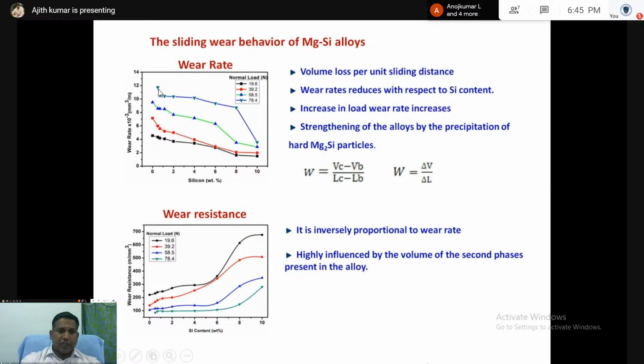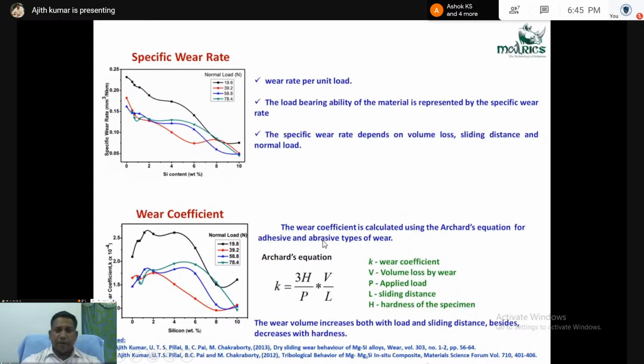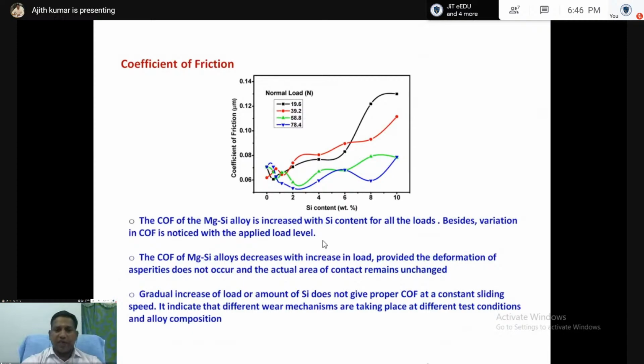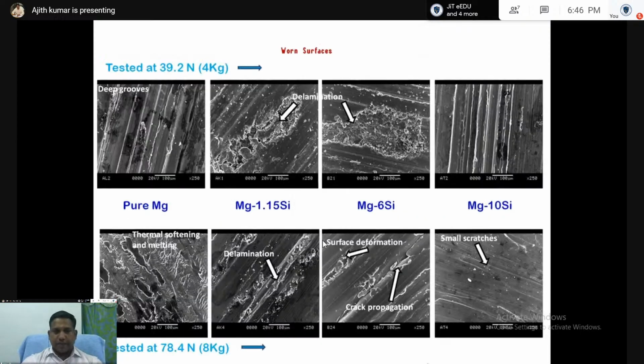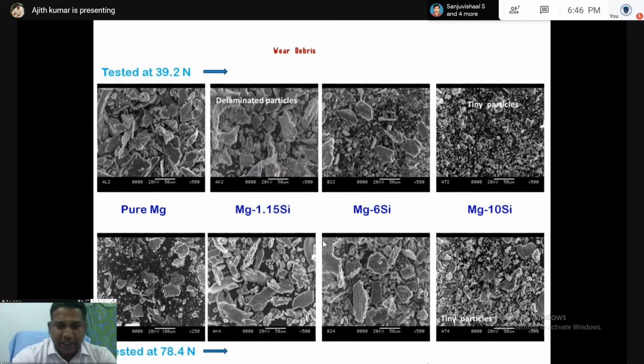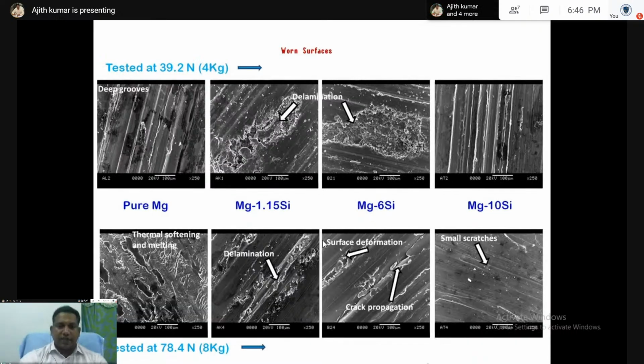So with respect to the silicon addition, the wear rate is reducing, wear resistance is increasing. Then we can make a graph of specific wear rate, wear coefficient, and coefficient of friction value that we can calculate using that data. After that testing, we analyze the SEM of all the wear samples, the worn surface and wear debris. These are the wear debris of different samples. These are the worn surfaces of different samples.